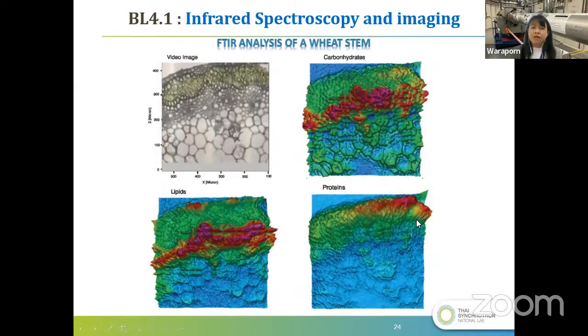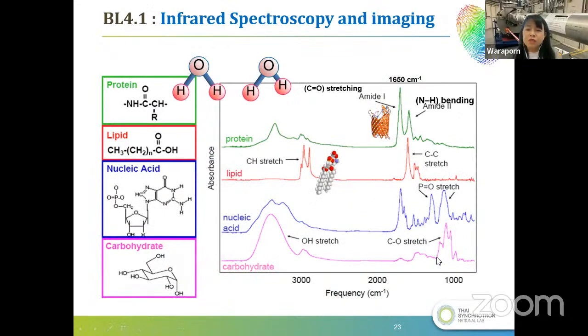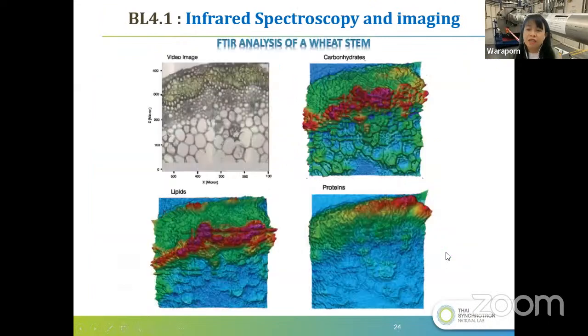So if we do mapping or scan, we prepare the sample by cross section first to about 4 micron thick, and measure FTIR under the microscope. Automatically, we can get the full picture of biological molecule localization. Like for carbohydrate, we can do the integration of the peak of CO stretching here. When we integrate the peak, we can see which area has higher intensity of this CO peak.